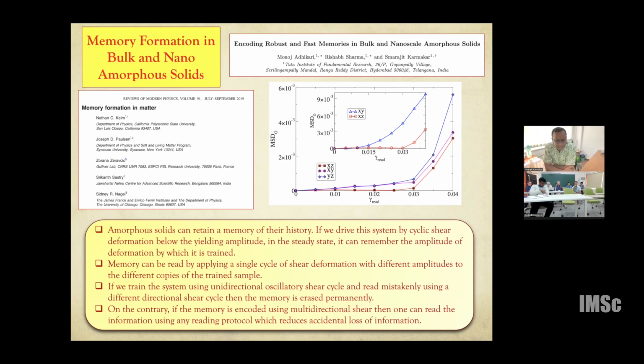If I ask you a question along the same line, let's say I do the same experiment with colloids. Can you point me to a good quantity to say that the system comes back to the same memory, because all that I have is positions of the particles? I think you can compute this mean square displacement from your initial sample. With respect to that, you will see the signature of the memory in the mean square displacement. For example, Sayantan probably showed that this is also encoded in modulus. If you can compute local moduli, then the modulus also shows a change at that strain amplitude. Those are much more global quantities, and they do have that information.